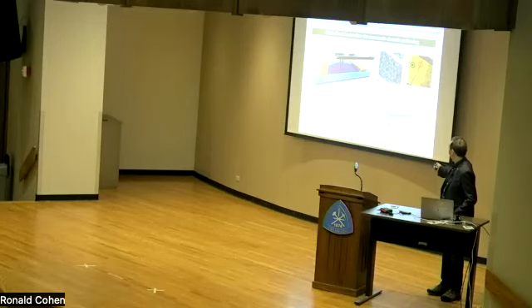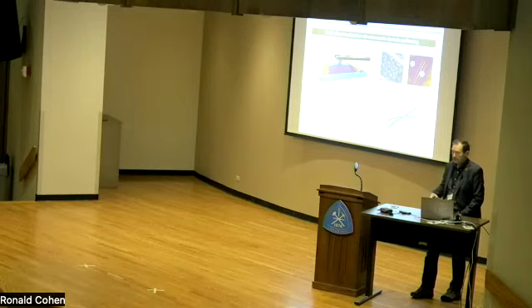The scaling here is enormous. If we relate it to the width of the domain bridge, we can talk about a characteristic scaling of approximately 10 nanometers. Of course, you're not limited to one linear domain, but you can write as many as you like, and the appearance of each additional bridge is accompanied by a change in conductance. So we can tune the conductivity of these systems by drawing specific types of domain patterns.